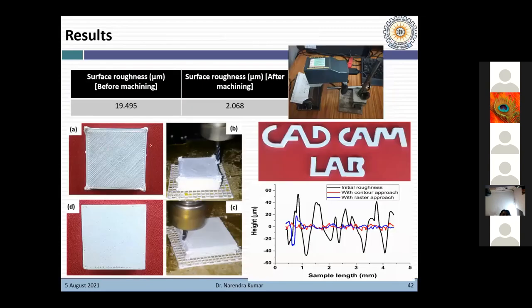So here you can see the results. If you look at this particular part, this surface is not that good, but this is after the machining operation. Before machining, the roughness was around 19.495 micron, but after machining, it was 2.068. In this graph, you can also see CAD/CAM lab written after machining, right? You can see the quality of the job surface; it has a very good quality surface.